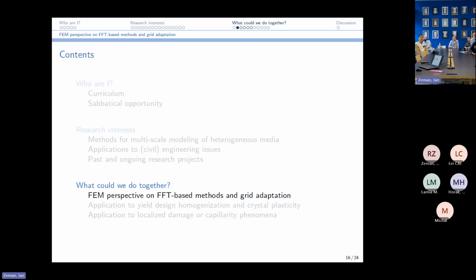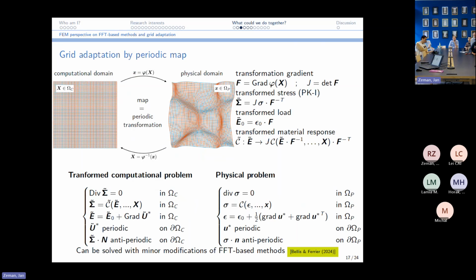So, what could we do together? I contacted Jan Zeman to work on this FFT-based method, and usually they are designed to work traditionally on a uniform discretization grid. Recently it has been introduced that you can transform that grid and actually work on a transformed grid, where you define your physical problem, with maybe a higher density of mesh points where of interest, and then pull back this problem to the computational domain with a regular grid, by doing things which we are used to doing at large scale. But now the transformation for this mapping is not related to the physical displacement. So if you have a linear elastic problem on the physical domain, then in the computational domain it will stay linear.